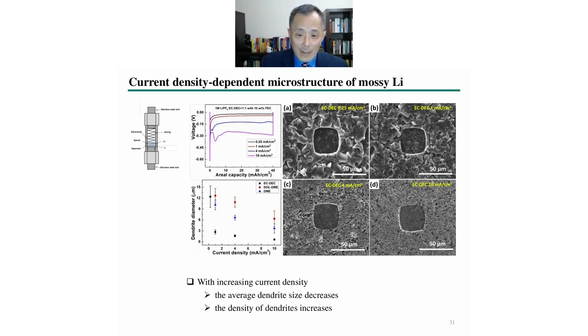Shown here are electroplated lithium using different current densities. At low current density, we see the dendrite size is larger than that from electroplating under high current density. And we also found that the density of dendrites, of course, increases with the increasing current density. This highly porous lithium is known in the community as mossy lithium. So what would be the mechanical property of such a mossy lithium?